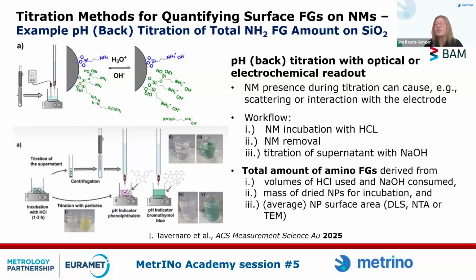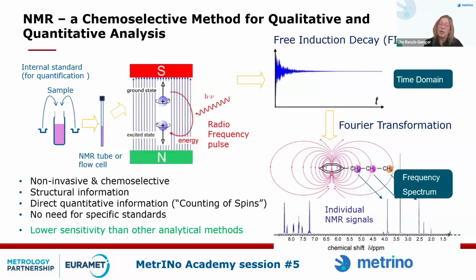So here you have the incubation of the nanoparticle, for instance, for the aminated groups with HCl, then you remove the particles and you do a back titration of your HCl solution with NaOH and then determine the volume needed for these titrations. You know the mass of the particles and you need the surface area, and here you are. So this is a relatively easy way of determining functional groups like amino or carboxylic acid groups, but you can also use NMR. For quantum dots, you can measure ligands directly by NMR. For other nanoparticles, it's a bit more complicated, but it's possible.